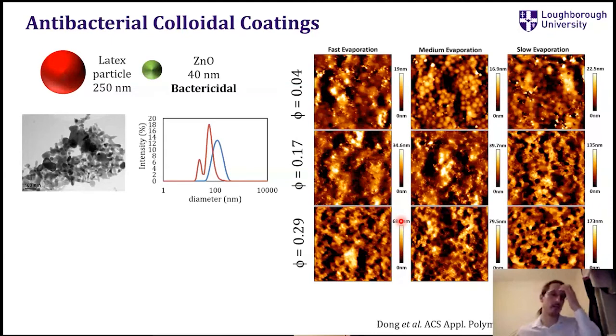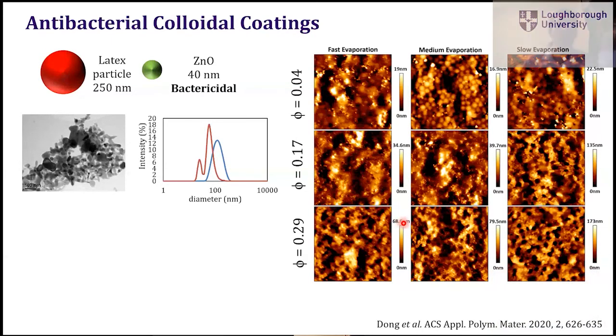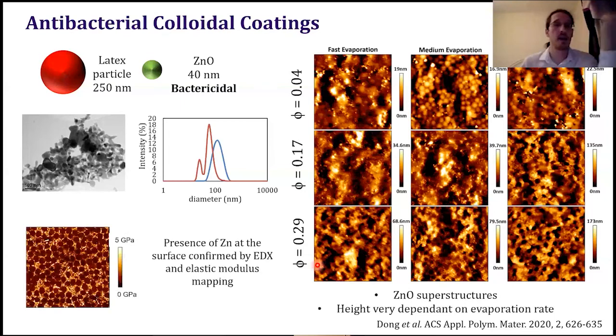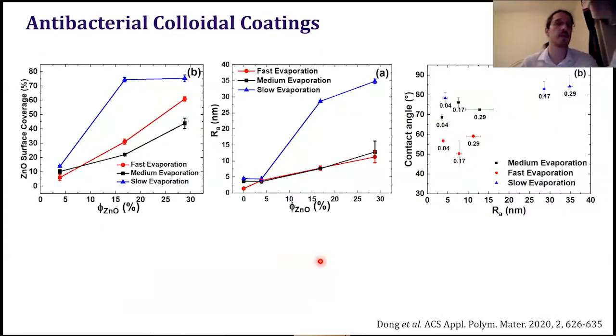And then by doing image analysis, we were able to see how much zinc oxide is at the surface for different zinc oxide concentrations and different evaporations. And as you can see in the graph here, for the slow evaporation rate, we reach the highest surface coverage, and also at the lowest zinc oxide concentration. So it looks like the slow evaporation seems to be reaching the better surface coverage by our bactericidal agent. But it also increases quite a lot the roughness, which might be also related.